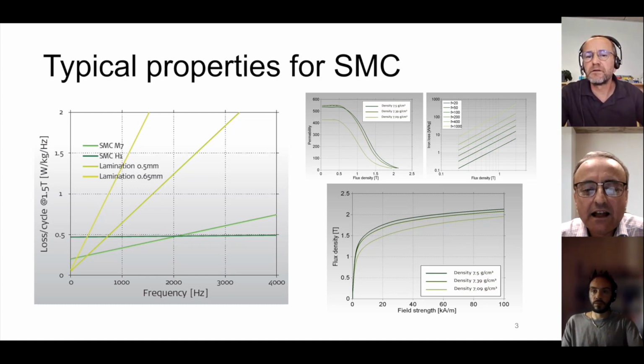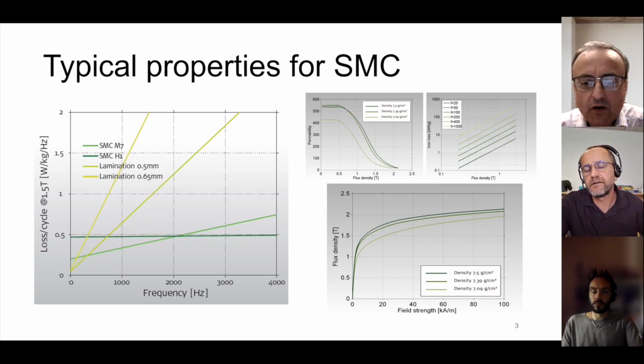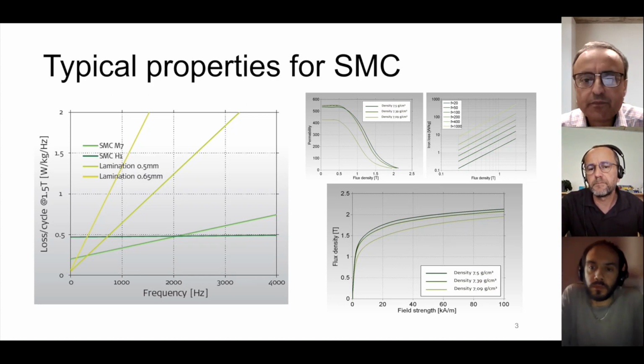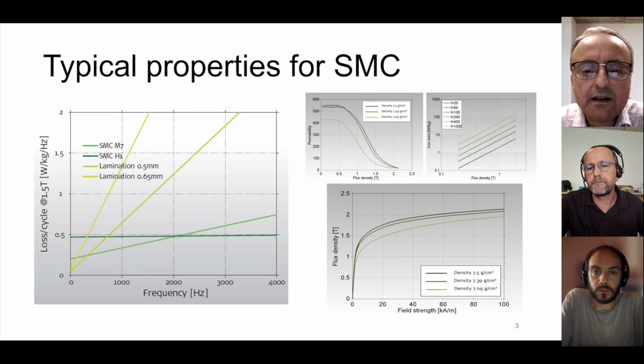Yes. And for the other properties, it's interesting to see that we can reach pretty high flux density values, but on the other hand, you need a pretty high value of field strength to achieve that level of flux density. So you have to keep this into account in the design of your machine. Typically, the permeability, and we can see that very well in that diagram.